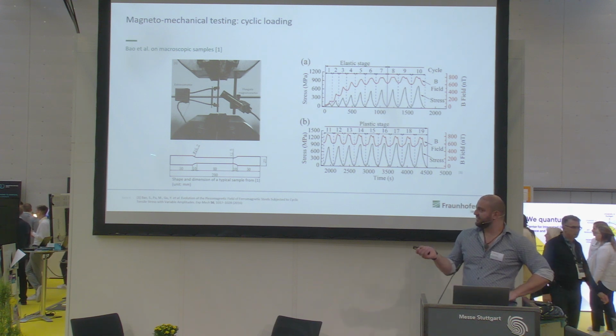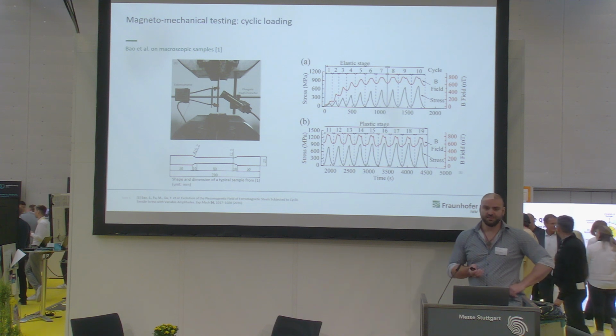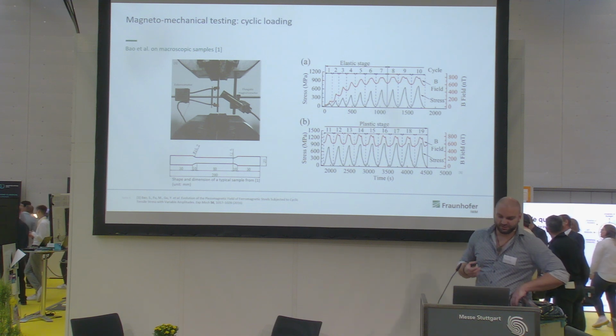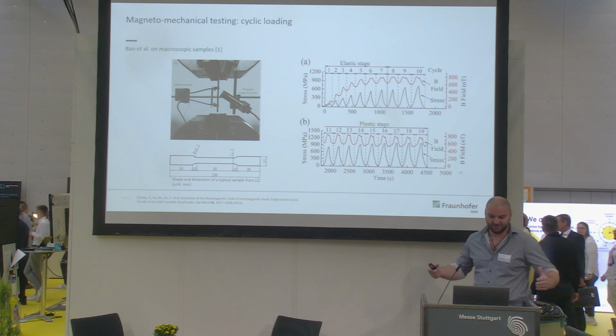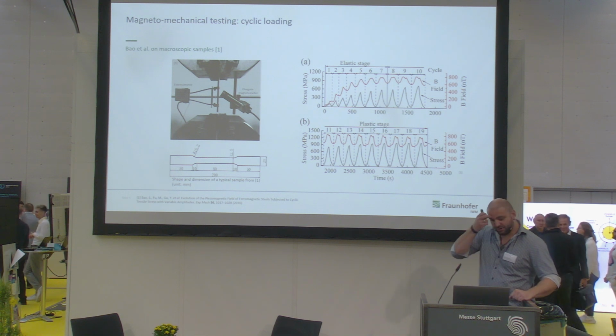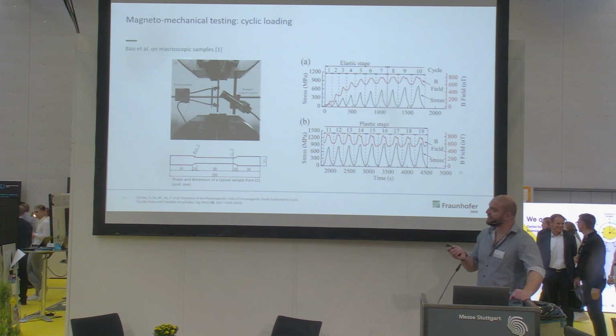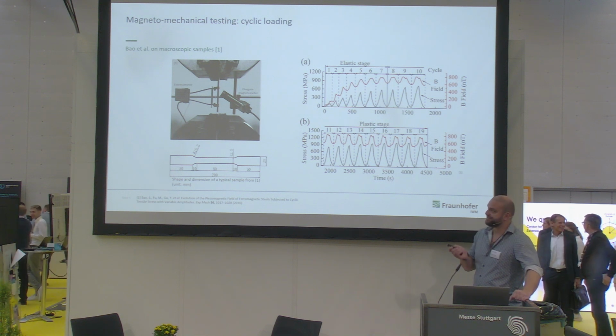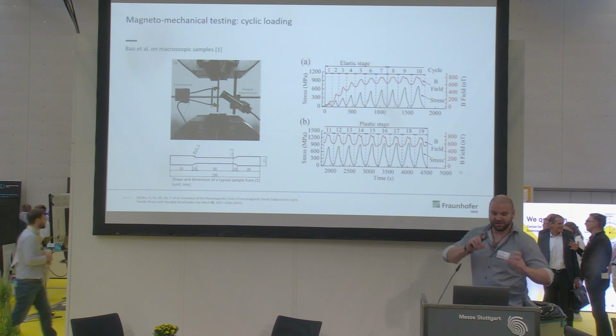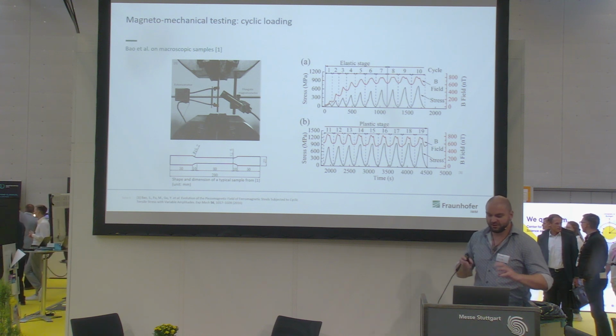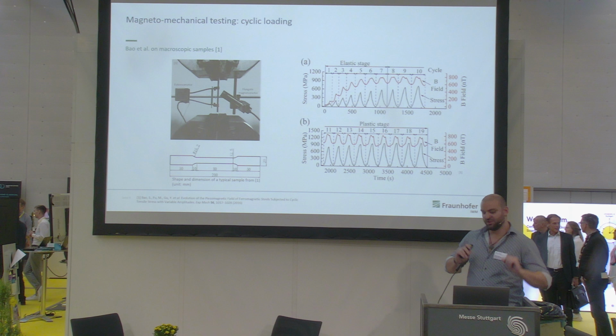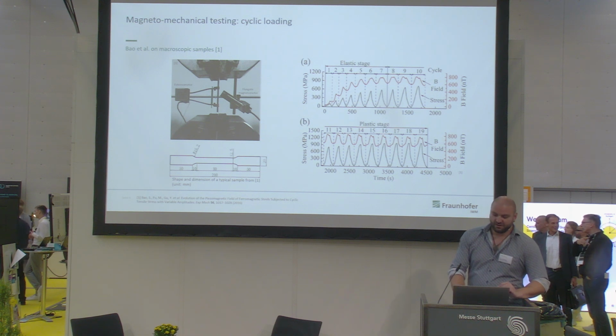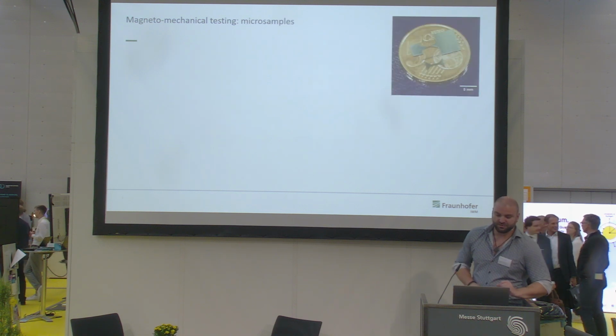Now, as I said, this is done on very macroscopic samples, and this holds, of course, some drawbacks. You need a lot of material, you need large samples, and also the fatigue is usually a little bit more statistical. You have maybe certain areas where cracks are forming, and it's not in a very controlled way. So what we do in our group is use very small samples.